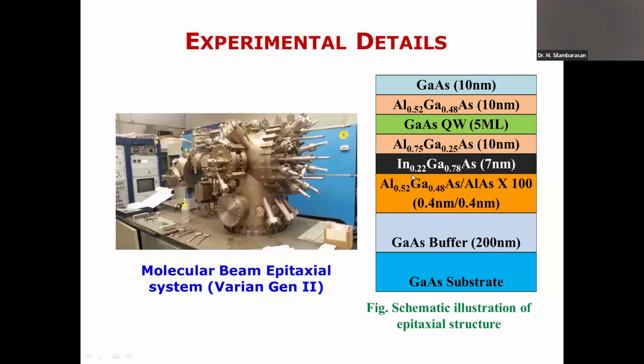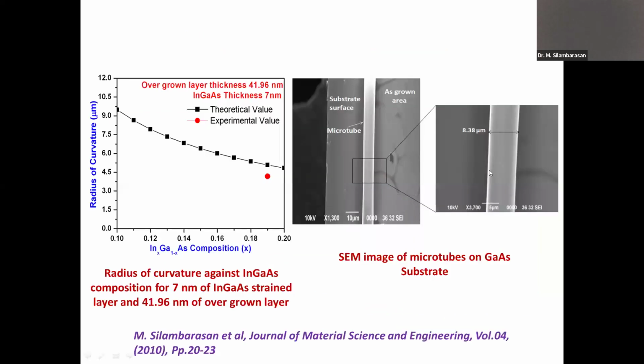microtubes. So actually this layer's thickness is only a few nanometers, but when it's formed as a structure, it is elevated into a microstructure. For the first time in India, we developed these microtubes on gallium arsenide substrate, and we calculated their elevation, the radius of curvature. This radius of curvature is in good agreement with the theoretical value as well as the experimental value.